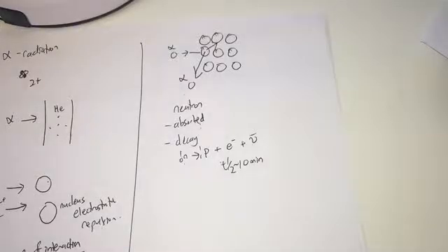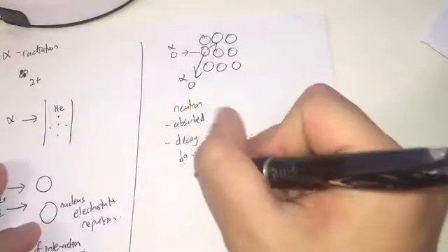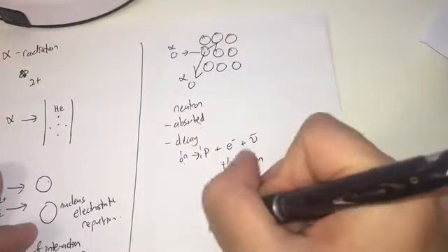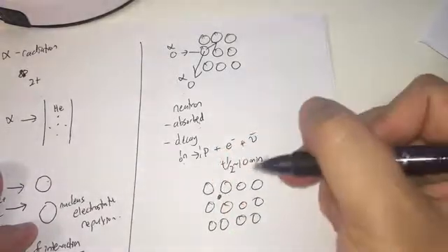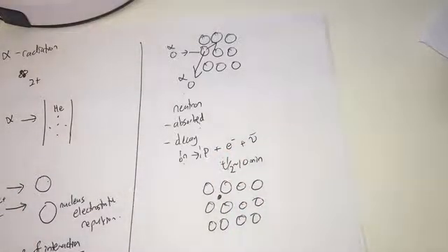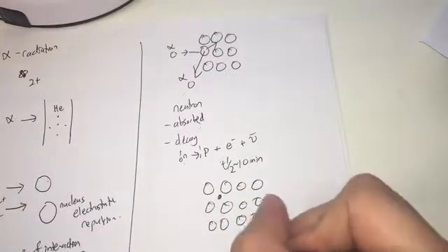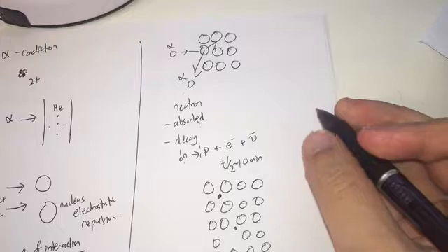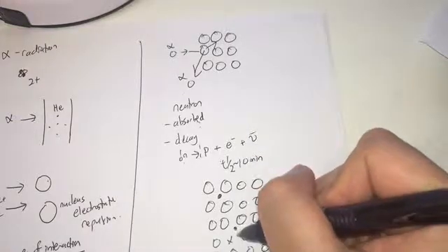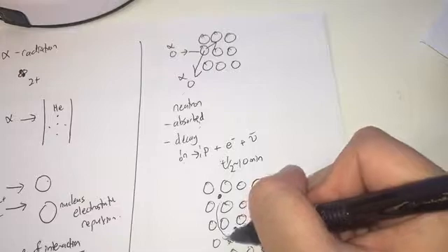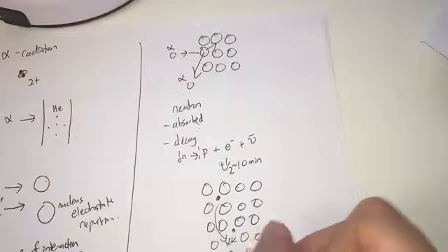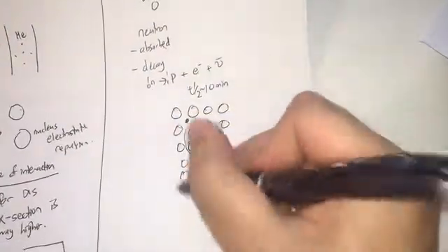But for the alpha, it will not get absorbed in case it comes to rest as a foreign interstitial atom inside the lattice. So let's call this an alpha. It will get lodged inside there. If you find a vacancy in the lattice, so let's say you have some alpha here, it will start migrating towards this vacancy. So alphas will tend to migrate towards a vacancy, and when they cluster together, they can form helium bubbles.